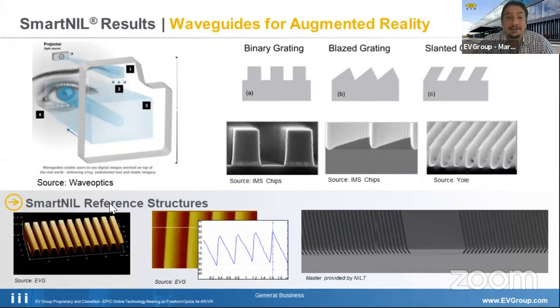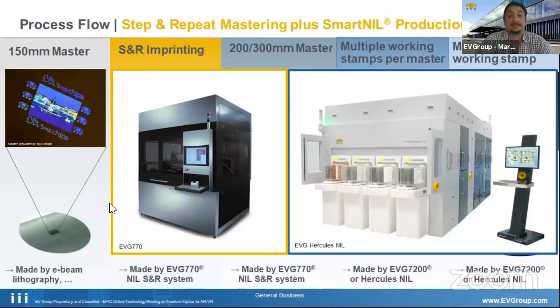And of course, there is literature on what structures can be used for waveguides and augmented reality, and basically we have reference structures for all. So for example, for NIL technology, Jose knows them also very well, provided us even these very fancy looking slanted structures. But from binary, to blazed, slanted, or whatever structures, we can do anything that's required here and replicate in a single shot, very efficiently in functional materials. And if you have a master, we can go for the step and repeat imprinting and directly to high volume manufacturing with our systems. We have this all in place also here at headquarters so that we can give it a run for the development.